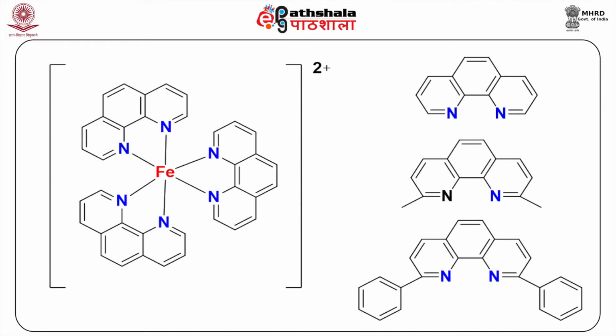It was found that a combination of steric hindrance due to bulkiness and an electronic influence of the substituent on the basicity of the coordinating N atom are responsible for the influence on the spin crossover behavior. The paramagnetic property of the complex increases in the order Y equals H, CH3O, CH3 and Cl. One has also found that a change of the substituents at positions not adjacent to the coordinating N atom in the phenanthroline ligand does not influence the spin state in comparison to the unsubstituted complex.